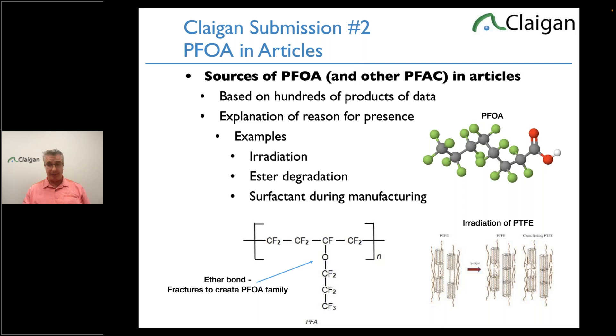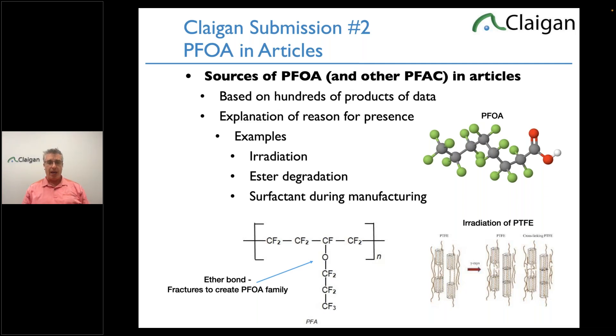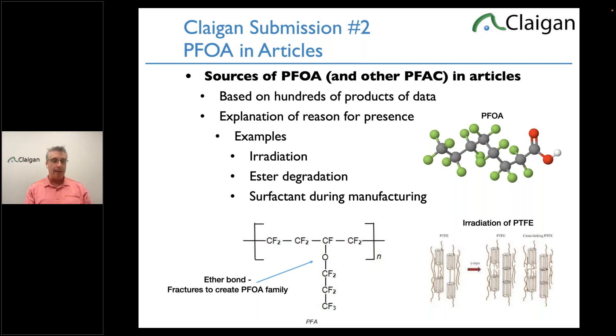If you take PTFE — which doesn't have PFOA at all — and hit it with gamma rays to make it rubbery, the gamma rays chop up the long chains. The chains reconnect and crosslink, becoming rubberized — useful for PTFE tape or ePTFE. Unfortunately some of these links react with air and become PFOA family. So in either case, it's a degradation product. Surface coatings on jackets — fluoroacrylates — have that weak bond. That bond breaks and creates PFOA family at different lengths. That's also why a fluoro spray jacket needs re-spraying every couple of years.